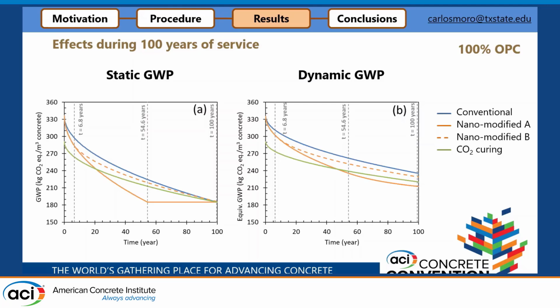And also you see that the dynamic normally accounts for higher final CO2 emissions, and it is because basically it's taking into account that you are emitting CO2 and you are not uptaking. And that is having an impact on the environment anyways. Even though you uptake it at year 100, you already made an impact. So we need to account for that.